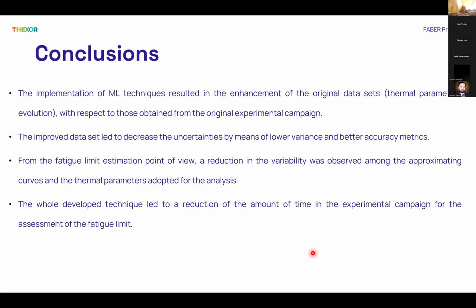And from the fatigue limit estimation point of view, a reduction in the variability was observed among the approximating curves and the thermal parameters adopted for the analysis, and the whole developed technique led to a reduction of the amount of time in the experimental campaign for the assessment of the fatigue limit.